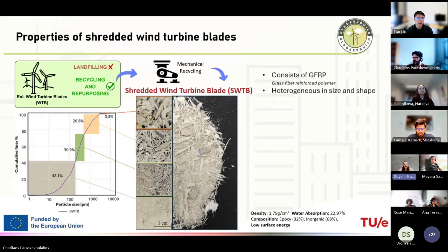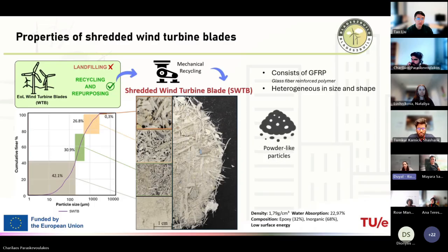Thank you. So here I would like to mention the shredded wind blade waste. It is explained previously. This is a method instead of landfilling. So this material we received from our partner PreZero, which contains almost 40% of the powder-like, and the remaining part is, as you see, fiber-like materials, which is very heterogeneous in size and shape. Also the fibers have problems on their surface. Their surface has a lot of flaws.